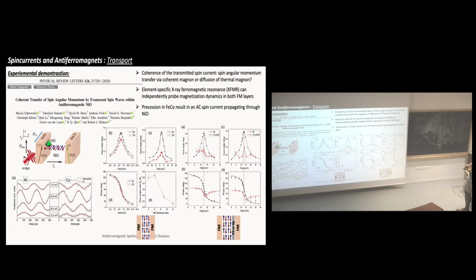But of course, there was one question: is it really coherently excited, or are these incoherent modes, for example with heat, thermal magnons, etc.? So there was this very recent paper where they tackled this problem. This time, they take one antiferromagnet, which is still NiO, sandwiched between two ferromagnetic materials which have two different magnetic resonances. They use X-rays, and they can probe either nickel here or cobalt here.